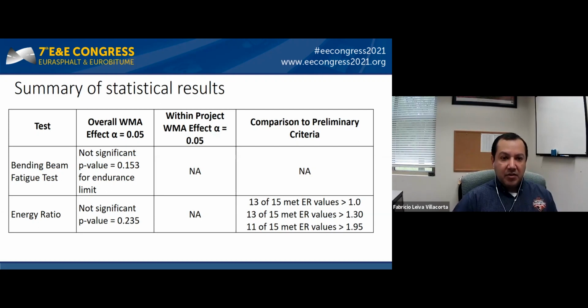And here I'll show you the summary of all the results, including the ones that I didn't discuss before. The first one is the bending beam fatigue test. In that case, we didn't find any significant differences for any of the pairs that we were comparing. We were comparing warm mix versus hot mix technologies. And for any of those, we weren't able to find differences, which is okay. I think as long as we didn't find anything negative or something that was below the performance that we were looking for compared to hot mix technologies, that was okay. We didn't have any preliminary criteria to compare with in that case.